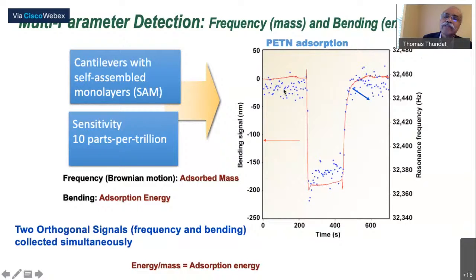And from these blue dots, we can actually calculate the mass using the resonance frequency. So resonance frequency and the bending are happening at the same time, and the frequency, remember that we are not exciting it, is the natural Brownian motion or thermal motion of the cantilever. And the bending is related to adsorption energy. So if we manipulate these two quantities, you can actually calculate the adsorption energy involved, and that basically says we have hydrogen bonding.